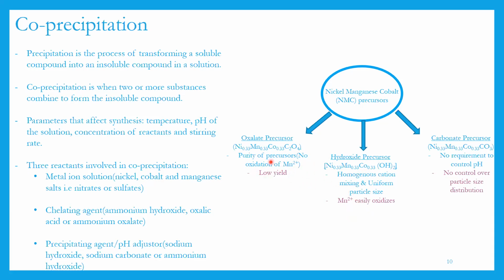The drawback of the oxalate synthesis is the low yield, because when you add lithium to this material, the C2O4 escapes as carbon dioxide gas, and it's such a big molecule. So the amount that you get is much less than what you start with. Let's say you start with 2 grams of this material, you add lithium to it, you do your high temperature synthesis, and you get about 0.8 grams back. That's not good. You at least need to get 1.5 or a bit more.